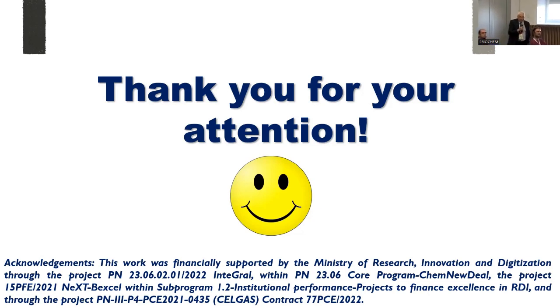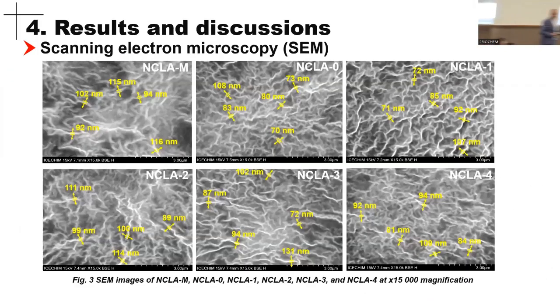Okay, you had a very nice presentation, with a lot of data. My question is, did you measure the diameter and the length of the nanofibers? And are there differences between hydrochloric acid and lactic acid? Not yet, but I have made some measurements on the diameter, if you have seen. There is a small difference: the ones obtained in the presence of hydrochloric acid have a slightly higher diameter. But I think some images do not help us to measure the length of the particles, because you can see that they are agglomerated, they are overlapping, and we cannot measure the length of the fibers. Maybe by another method, sometime.